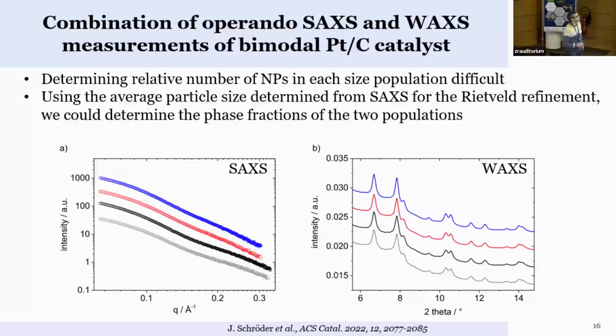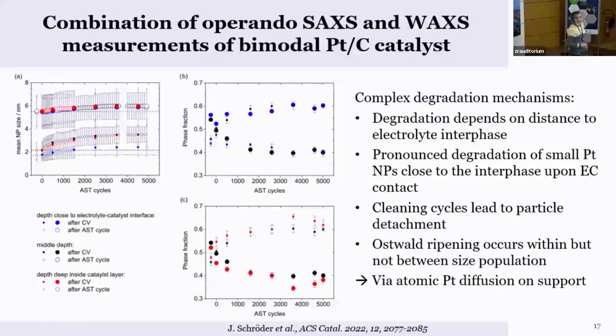So what we had to do in order to get this information out, we took the results from the SAXS about the average size and used that in the Rietveld refinement, and then we could determine the phase fractions of small particles to large particles. And what we saw is also, depending on where you are in your catalyst layer, the change in size, but also in phase fraction, so the ratio between small and large particles, depends on where you are, if you're close to the electrolyte or more in the middle of the catalyst. And it was really complex to analyze this.